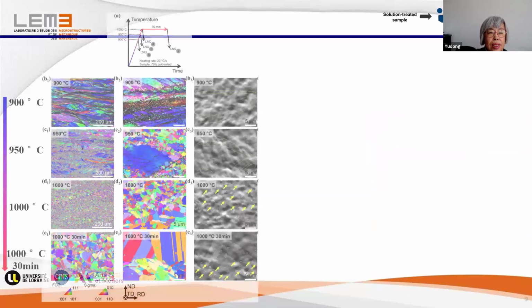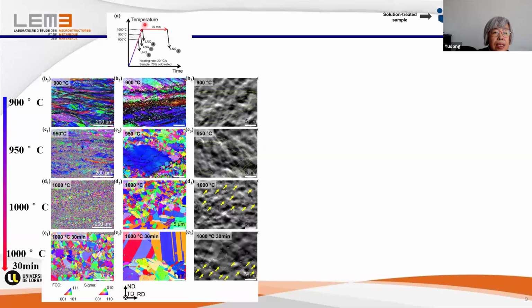And then we did heat treatment and ex situ examination by SEM EBSD. We heated the material with the same heating rate, which is very quick, to 900 degrees C and these three temperatures. We cooled the material in liquid nitrogen to freeze the heated microstructure, and then did the examination.